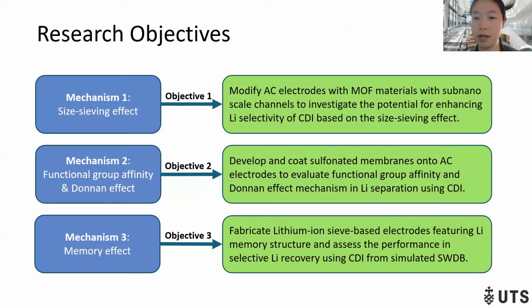Building on these three strategies identified from the literature review, my PhD research aimed to explore these three different mechanisms for enhancing lithium selectivity in CDI systems. Based on the first strategy, the size-sieving effect, the objective is to modify the activated carbon electrode with MOF material that has sub-nanoscale channels, to investigate whether physical ion size exclusion can improve lithium selectivity.